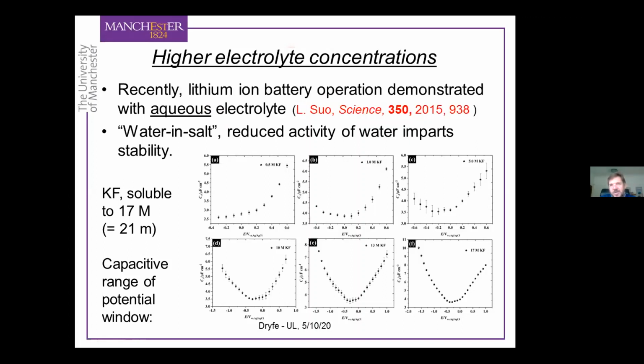So the idea is quite simple if you think about it. If you have a very high concentration of salt, so there isn't enough water to solvate the salt properly, then the thermodynamic activity of the water decreases, and basically it becomes hard, if you like, kinetically, to oxidize and reduce the water to do the hydrogen and/or the oxygen evolution reactions. So you extend the potential window of the water to such an extent that you can intercalate lithium into graphite, even though your solvent is water.